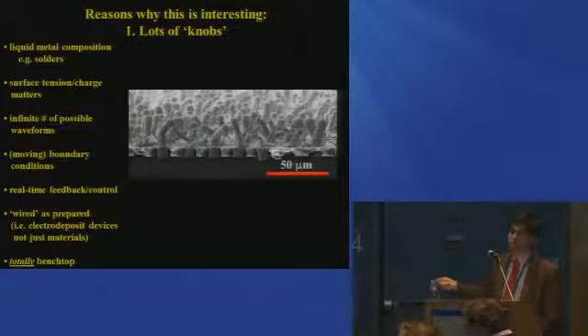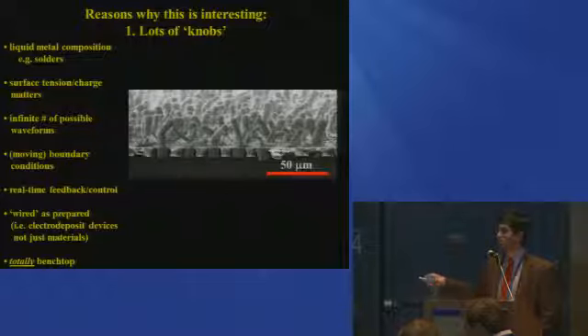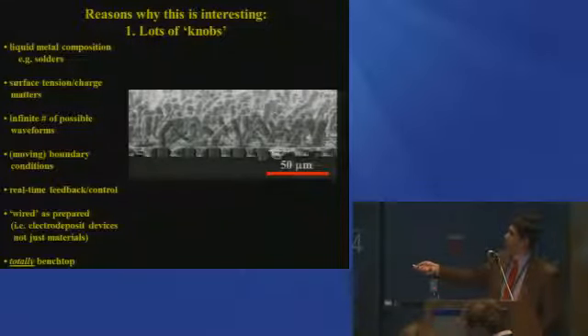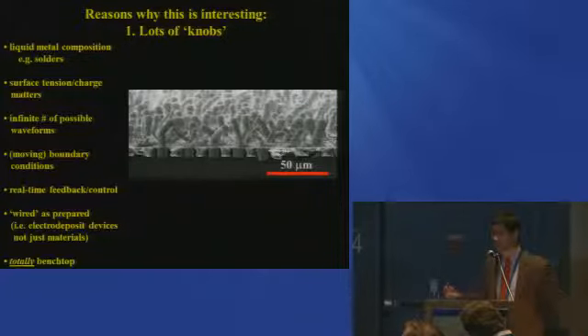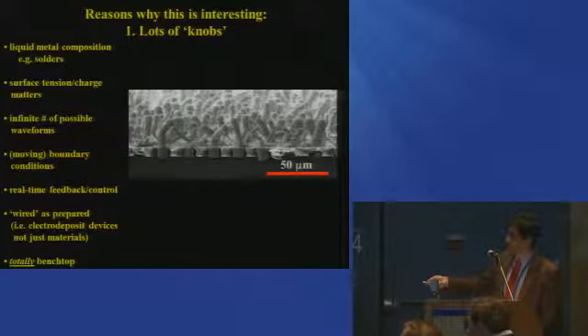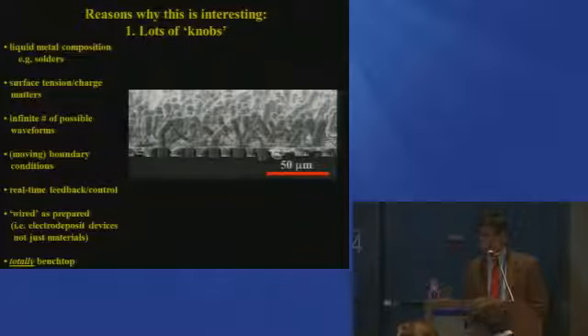This represents a moving boundary condition if you think about it. This electrodeposition process, the active spot, is at the top, not at the base. So as you grow the crystal, and the crystal growth rate changes where you're at relative to the diffusion length and diffusion layers, you have a possibility of growing crystals with feedback in real time, and it gives you control that you don't have in any other possible process that I know about. And finally, these are not just materials, but these are wired to an electrode substrate. So you have the capacity to make devices directly, not just materials.